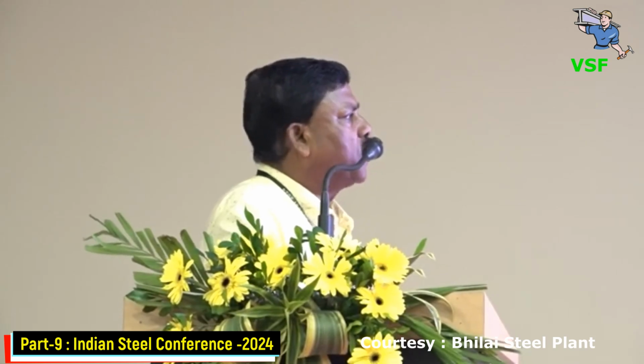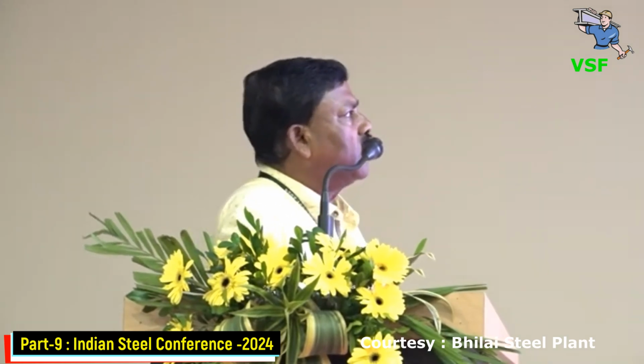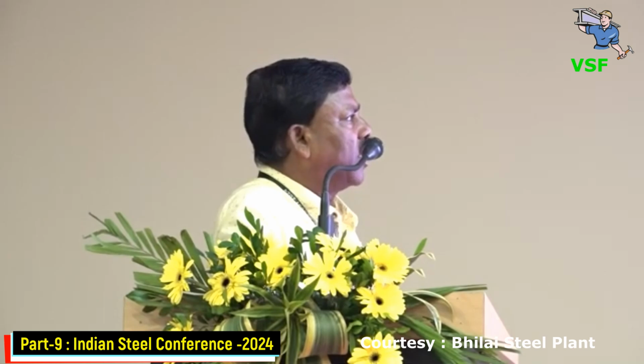Generally when we procure bricks, we go for normal cold crushing strength and porosity. But what is more important is after coking, because when the converter is in operation the carbon is going, and then you get the coke crushing strength and coke porosity. More important will be the slag portion, the thermal shock resistance, and the optimization of residual carbon. For magnesia carbon bricks there are 2 major components, magnesia and graphite. While selecting the magnesia, what is very important is not only MgO; the impurities play an important role, like the lime silica ratio, which should be more than 2, so that you can produce dicalcium silicate and tricalcium silicate.